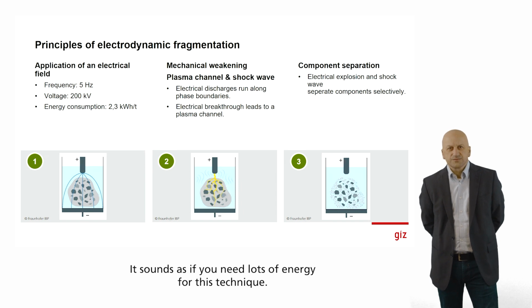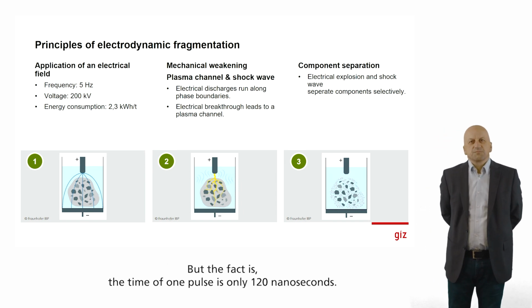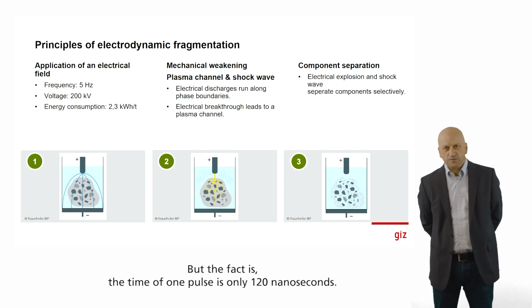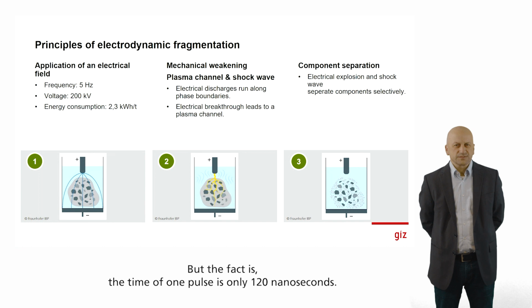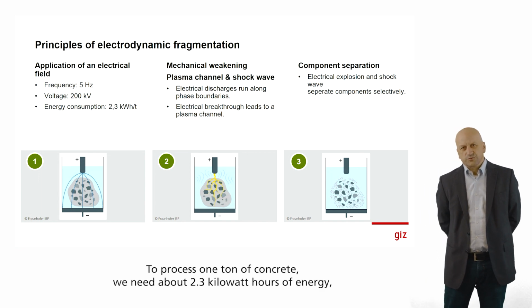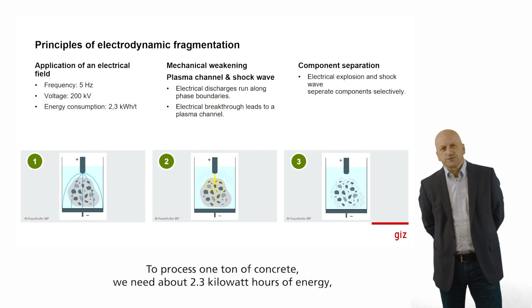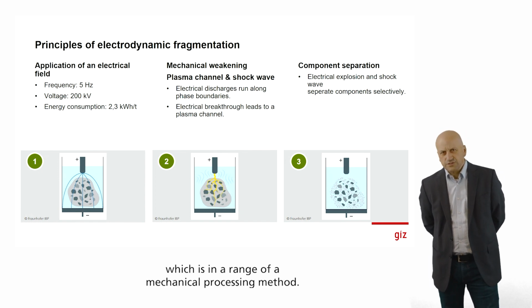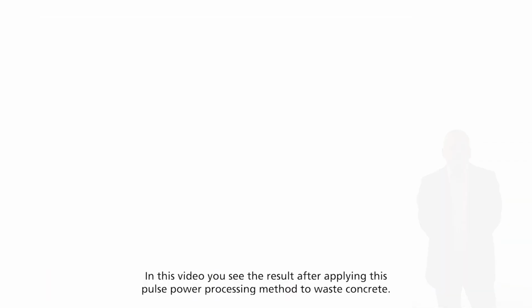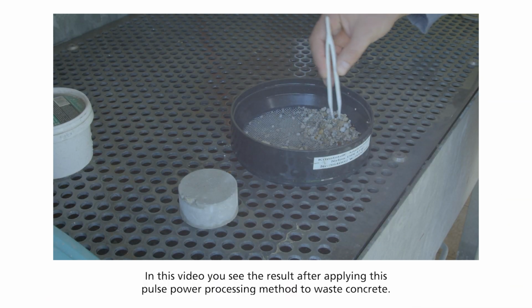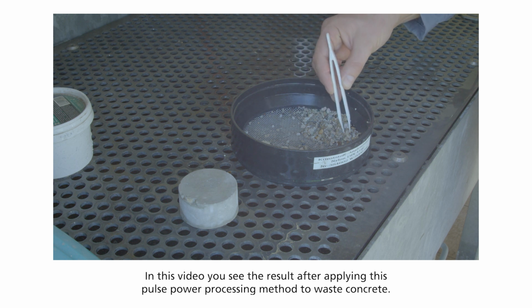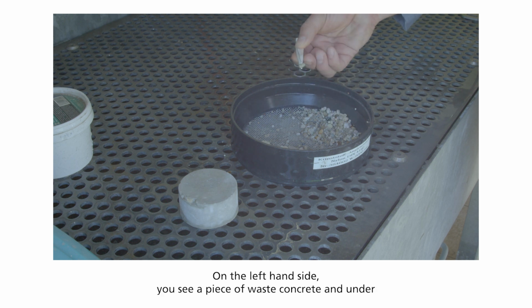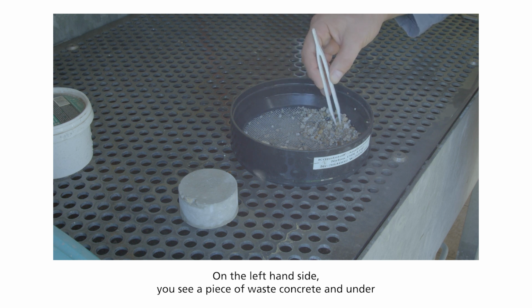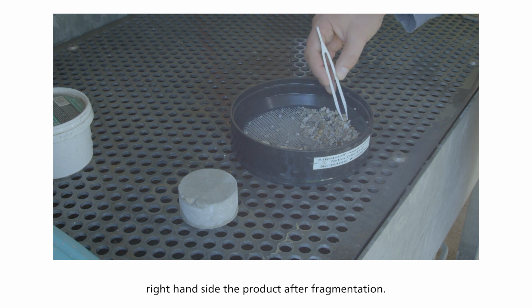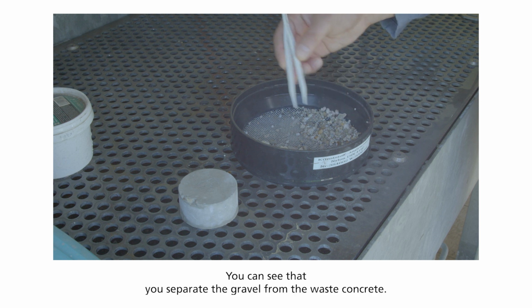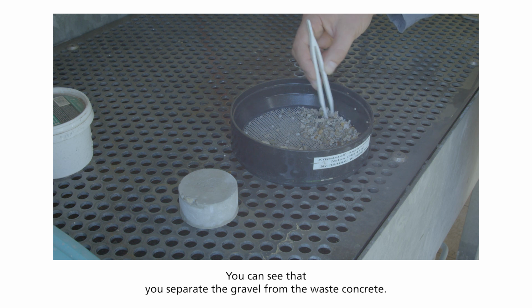It sounds as if you need lots of energy for this technique, but the fact is the time of one pulse is only 120 nanoseconds, and to process 1 ton of concrete we need only 2.3 kilowatt hours. This is in the range of mechanical processing. In this video you see the result after applying this pulse power processing method on waste concrete. On the left hand side you see a piece of waste concrete, and on the right hand side the products after fragmentation. You can see that you can separate the gravel from the waste concrete.